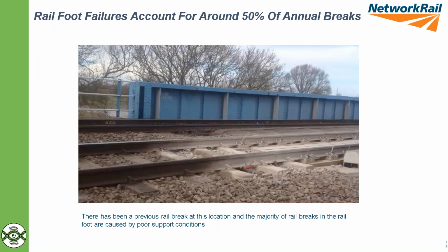A couple of examples of this type of failure, some very obvious. This is a site where we had 2 broken rails at this location, both of them foot failures. And in both situations, really, because we're asking the rail to do too much. The rail is effectively a beam in bending, and ideally it's supported by the sleepers rather than having the sleepers hung from it. So a transition area on a structure, but a common problem area, where we ended up with 2 broken rails at this location in older rail, but with a high fatigue damage because of large bending forces over a long period of time.